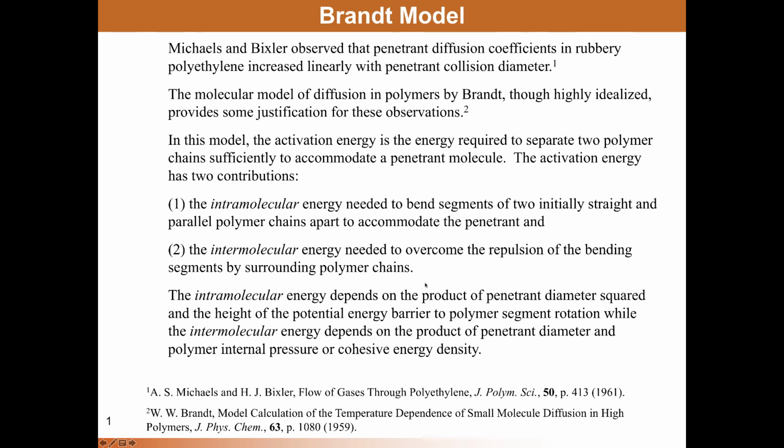That contribution depended on the product of not the diameter squared, but the penetrant diameter and the polymer cohesive energy density, or so-called internal pressure. And so the Brandt model has two terms in it, one proportional to the square of the penetrant diameter and the other proportional to just the penetrant diameter to the first power.